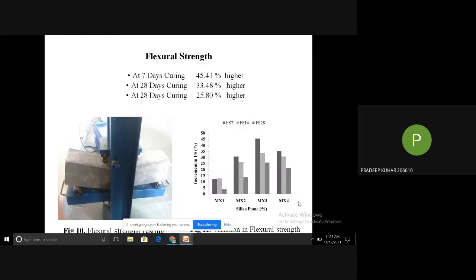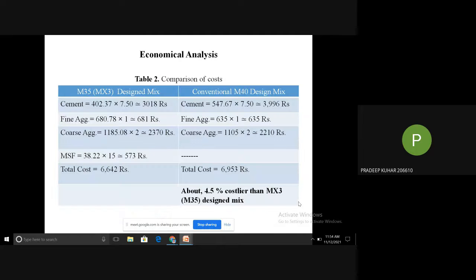After that, I also observed that the MX3 specimens had achieved the target strength of the next higher grade concrete. I had designed all the specimens for M35 grade concrete, but MX3 specimens with 9.5% replacement of cement with silica fume had achieved the target strength of M40 design mix grade concrete at 28 days of curing. Then I compared the economical aspects of the M35 design mix, in which I had used silica fume, and the conventional M40 design mix.